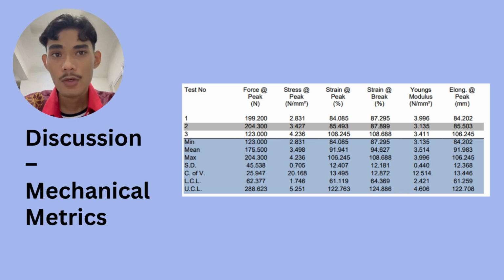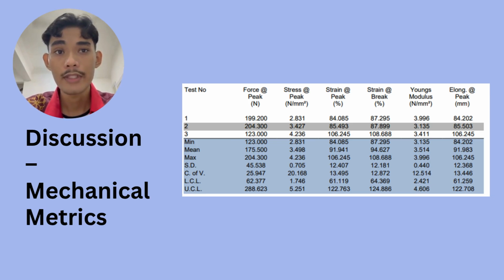On average, the peak force the material could handle was 175.5 newtons. The average peak stress, which is the force spread across the thickness of the sample, was 3.5 newtons per square millimeter. The most important number here is the Young's modulus, which averaged around 3.51 newtons per square millimeter. In simple terms, a low Young's modulus means the material is highly flexible and stretchy rather than stiff or rigid. However, we also notice a high statistical variation in the peak force, about 26%. This high variation confirms that the material is not completely uniform throughout the entire batch.